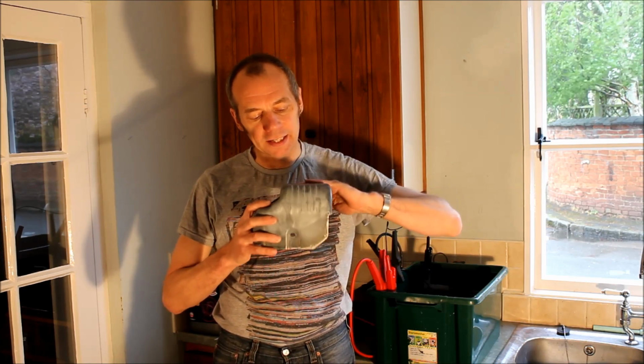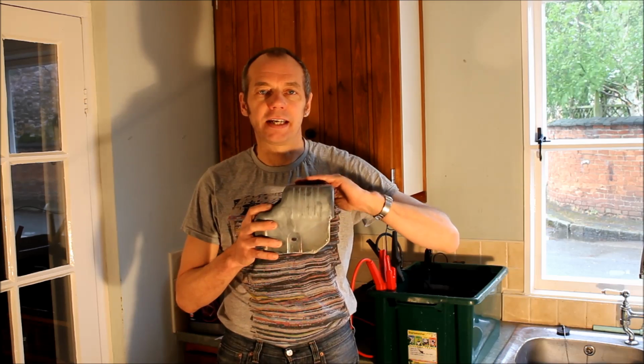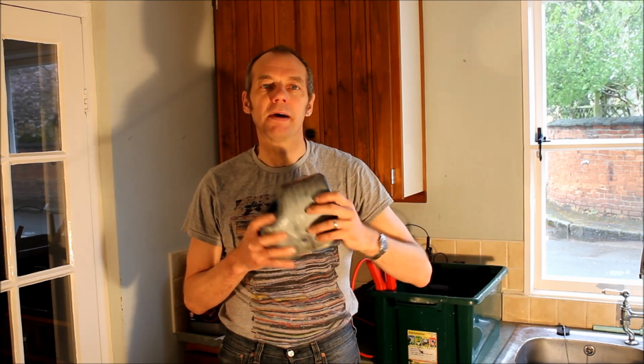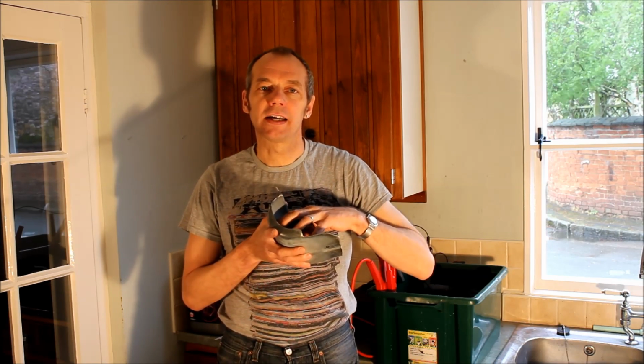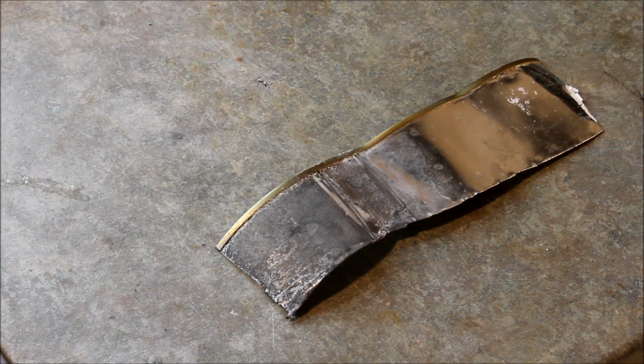The problem is that this convex outside, particularly the parts of the outside that are facing the anodes, they just get far too much current, so they're burning all the time. Meanwhile, the concave inside, you can't really get any current into there at all, so that hardly plates at all. And this is what burning looks like so that you know how to recognise it.